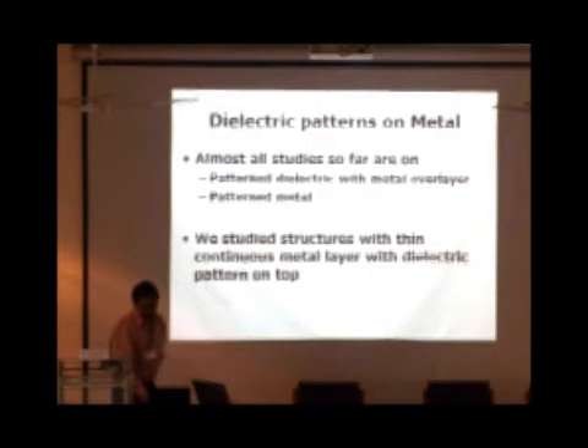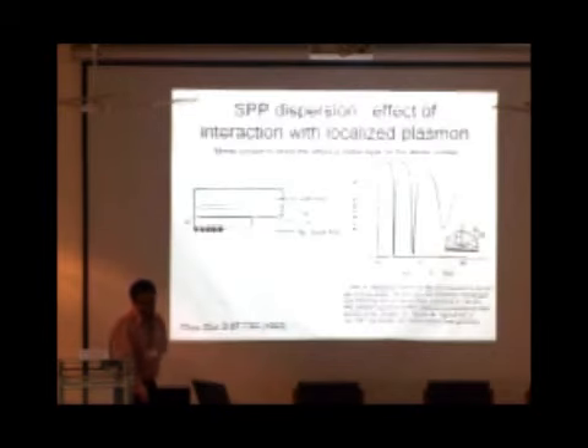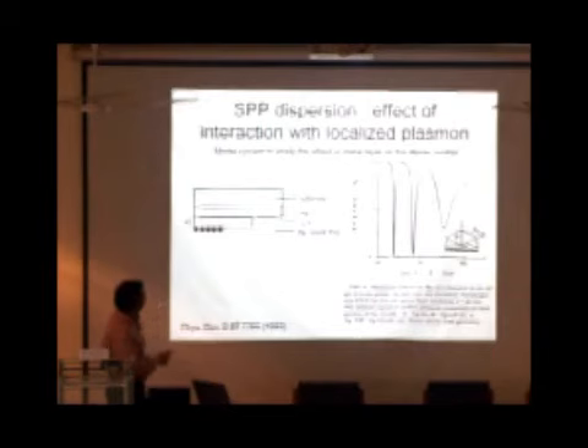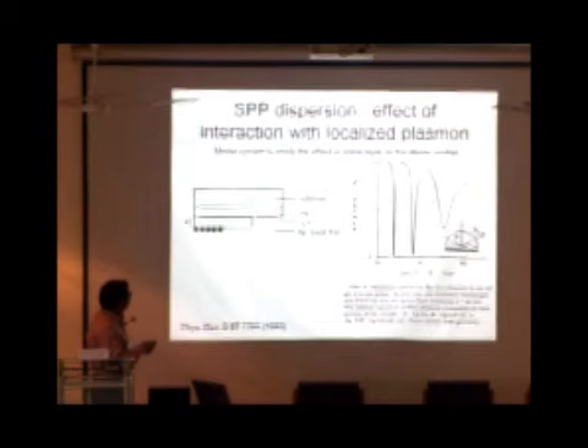Towards that, we looked at these structures. There are also different studies in literature - essentially you have a metal layer and then a dielectric layer on top of which you put metal nanoparticles, for example. By controlling this dielectric layer thickness, you can control the interaction between the metal layer and the metal particles.